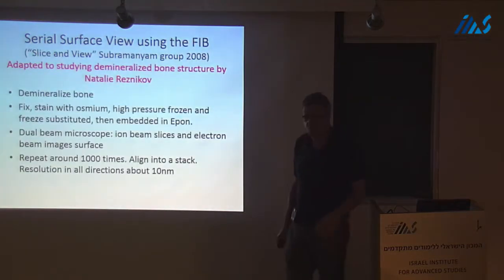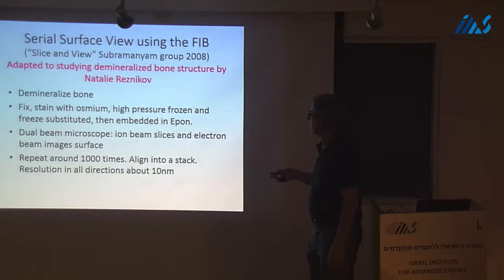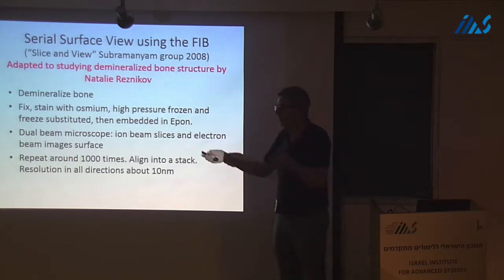Now, what's involved? Unfortunately, we can't image this with mineral present because there's just no contrast in this microscope at the moment. So you have to remove the mineral phase, and you fix and stain, but you use a lot of modern techniques, high pressure freezing.